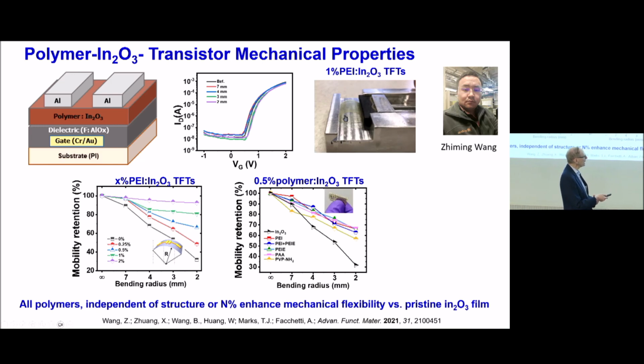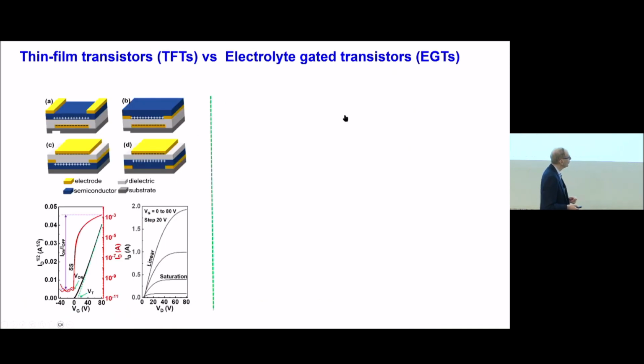And this is just showing as we bend the device more and more. You retain most of the mobility until we begin to finally lose it. So this is no PEI, and this is more and more and more. And you can see at this level, we've really kept a lot of the mobility. You can make PEI polymer indium oxide TFTs that you can bend. And these are different organic dopants that we use. And it works very well.